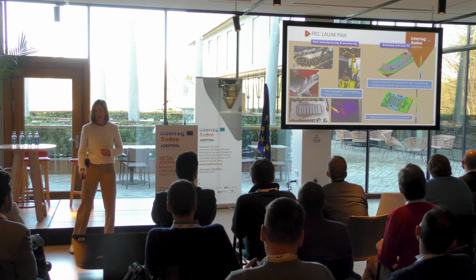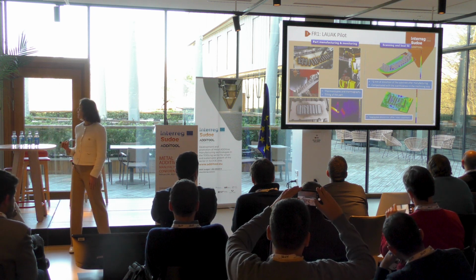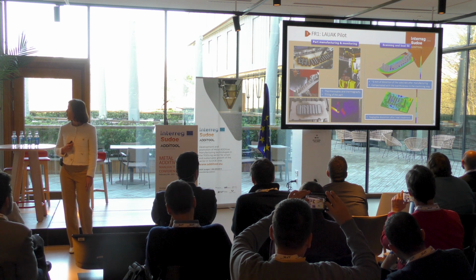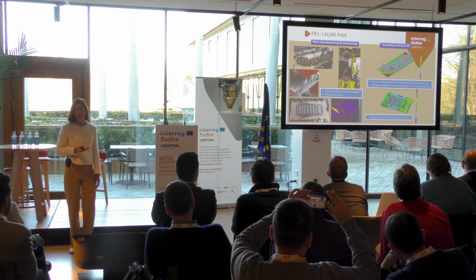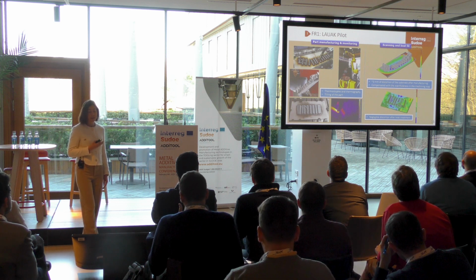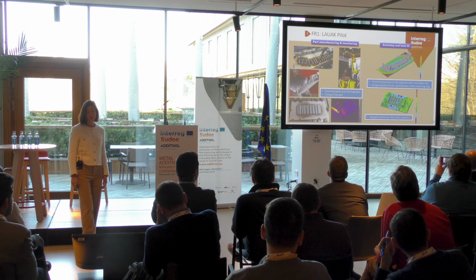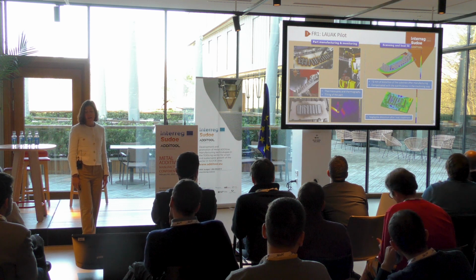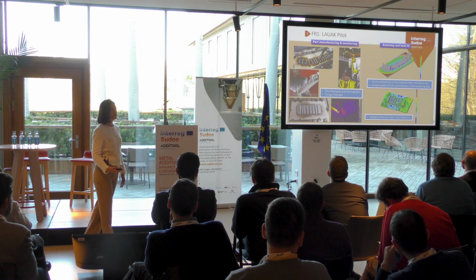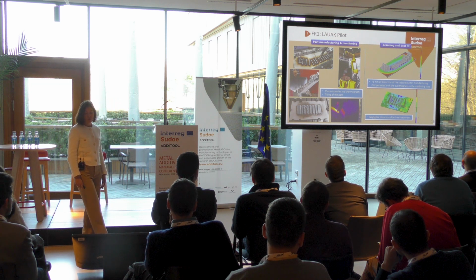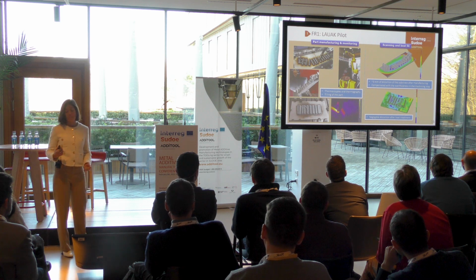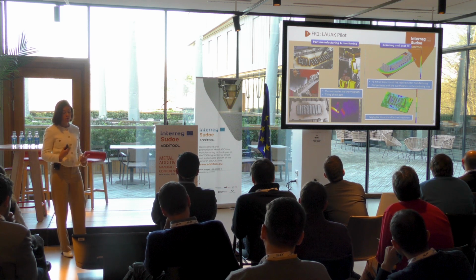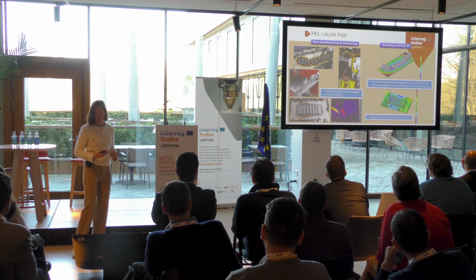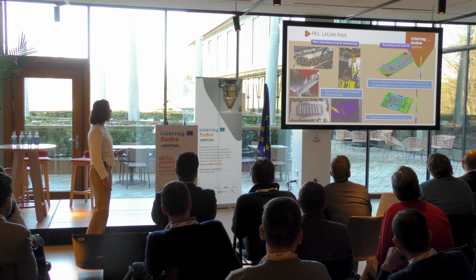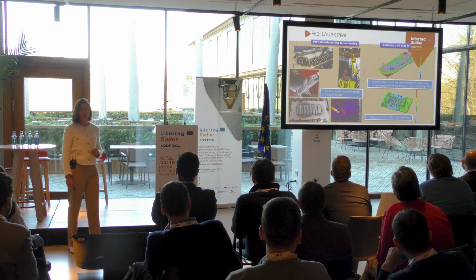Once we obtained the parts, we applied scanning to make the best fit with the original design, and there we could see that the final distortion was around 3 millimeters. But we could compensate for that in the final step of machining with the over-thickness applied at the beginning. We also saw the distortion due to the heat treatment, comparing before and after in the smaller part, and we saw that this distortion was negligible.